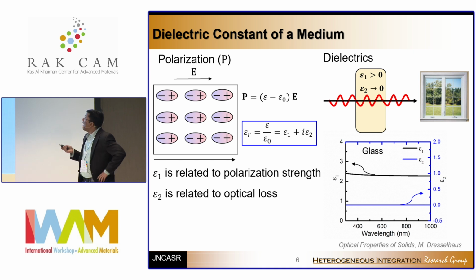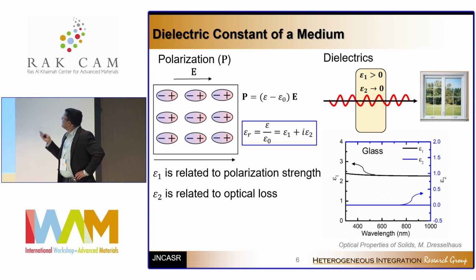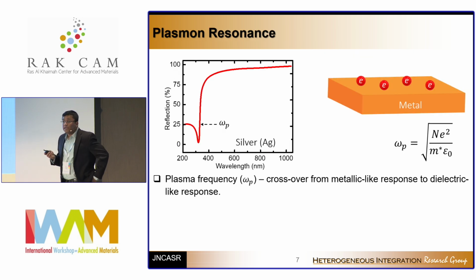If I take a glass, for example, window glass, and if I shine visible light in it, there is absolutely nothing in the glass. There is no vibration, no electron, nothing which can interact with the incident light. And that is why light pretty much just goes through. And that is why you see a perfectly flat, very low value of epsilon1, and pretty much zero loss. So that is a dielectric. In the case of metal, things get much more interesting, because metals have all these free